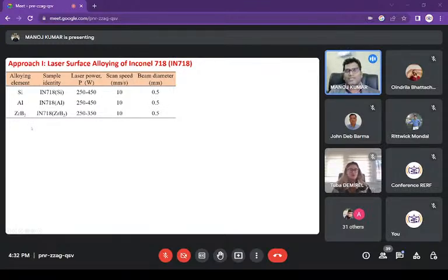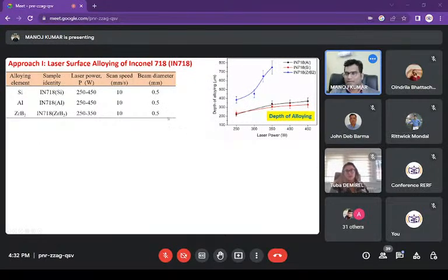What we achieved is that when we started alloying with varying laser power, we got different depths of alloying. Obviously, when we increase the laser power, the heat input will increase and the depth of alloying will increase. Interestingly, with ZrB2, the increase in depth of alloying was exponential, very high with a slight increase of laser power, and that can be attributed to an exothermic reaction taking place during dissociation of ZrB2.